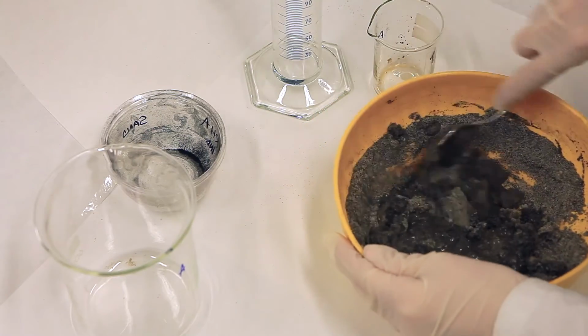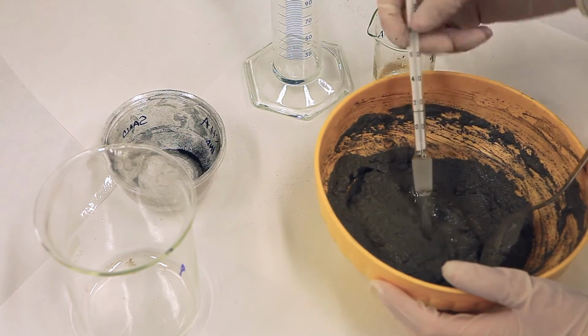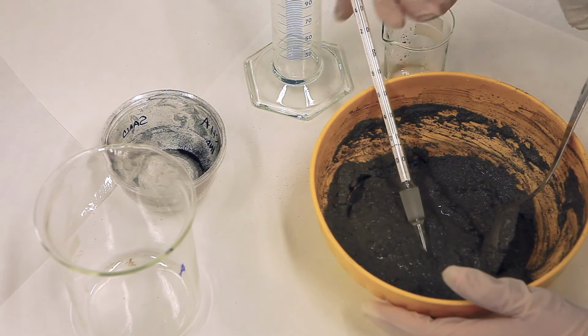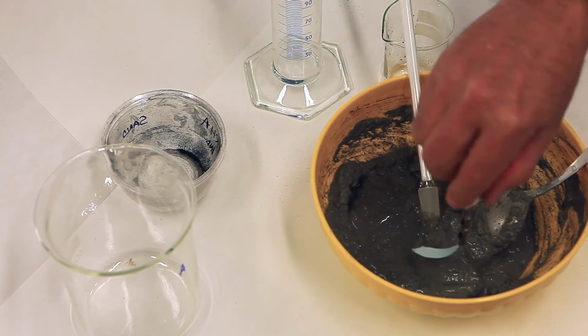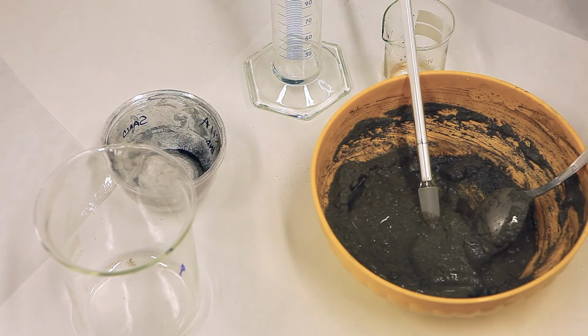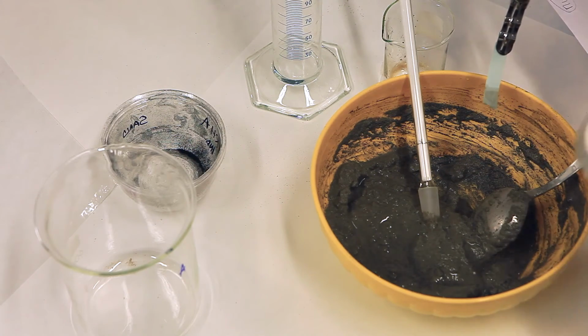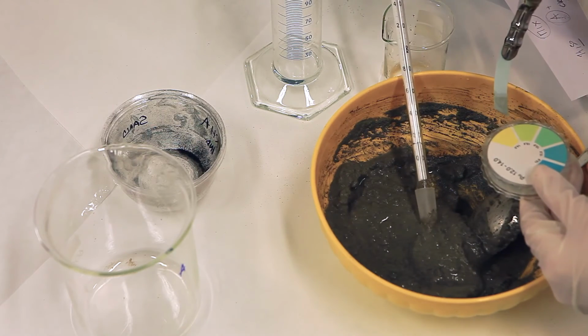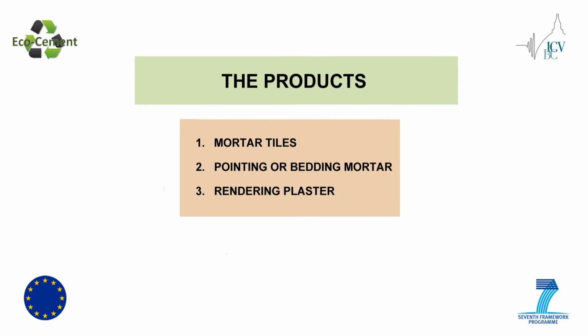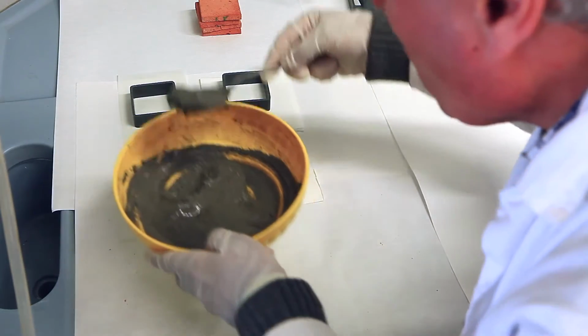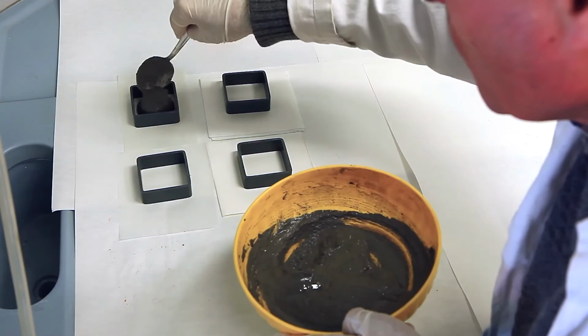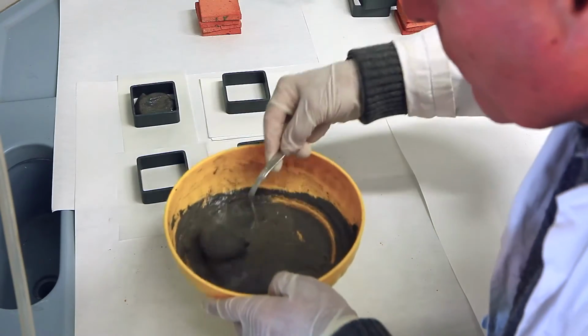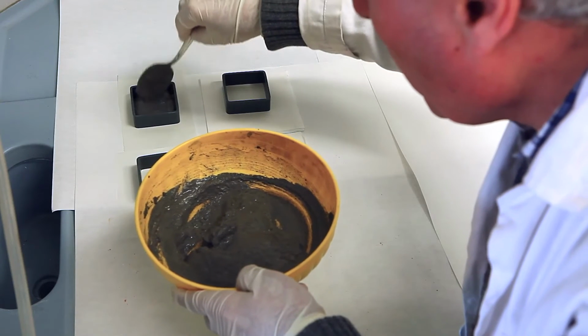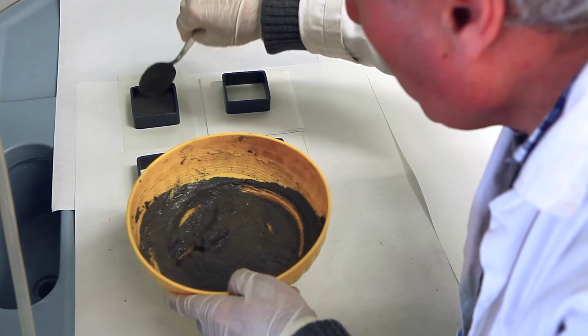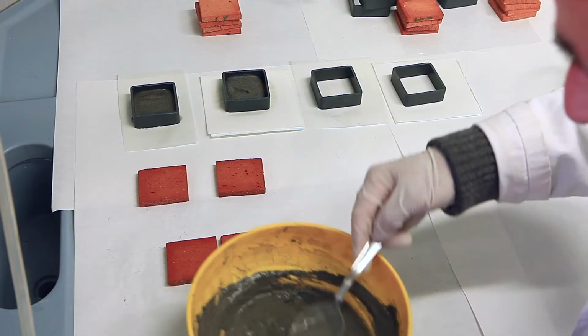All the components are blended for 3-4 minutes, controlling the temperature and the pH. After that, the EcoCement paste is made. It is poured inside the molds for small mortar tiles, with bedding mortar and brick support for the plaster use. Taking into account the amount of available lime, higher than 15%, present in the cement kiln dust, the final product can be considered an aerial mortar.